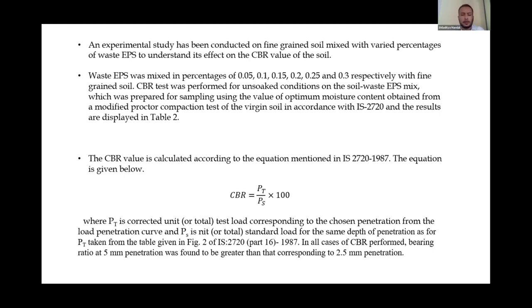Why do I call this waste EPS? Because after utilizing the product, we throw it. So it is not reusable again, and it is termed as waste EPS. So we collected some waste materials, and we did this rather than directly purchasing it from the market. Every test was performed in accordance with the Indian standard codes, and CBR is evaluated through this expression: PT by PS, where PT is the load taken by our soil sample, which was mixed with the EPS, with respect to PS, the standard load taken by the standard specimen.